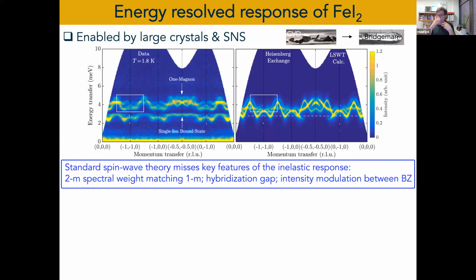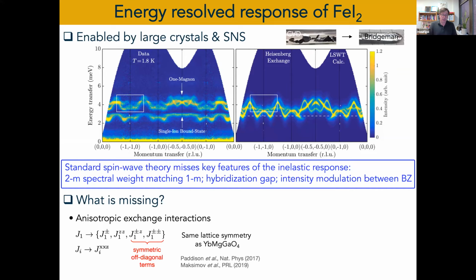So for a Bravais lattice, such as the triangular lattice, you should have the same intensity at all points of the Brillouin zone, at least in simple models. And so the fact that the intensity is modulated with a different periodicity than the lattice periodicity is a sign that there is something going on. So what we did here is to try to understand what is missing in our spin Hamiltonian. And what is missing is exchange anisotropy, as simple as this.